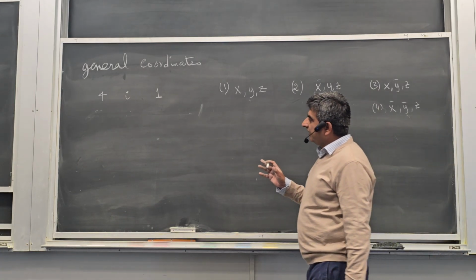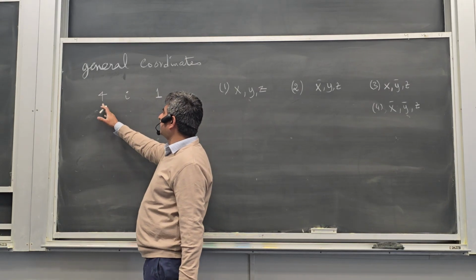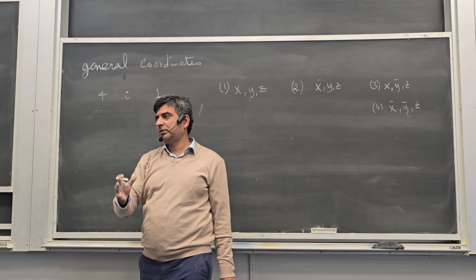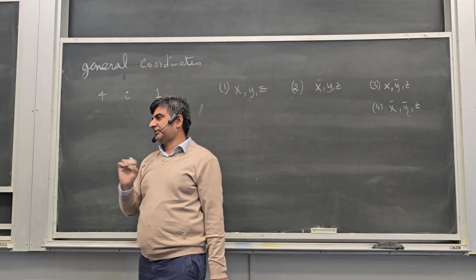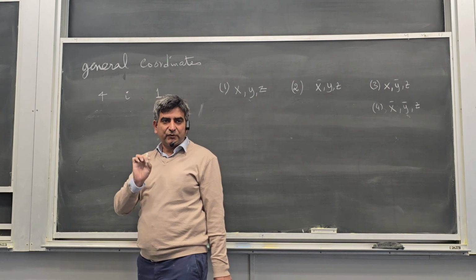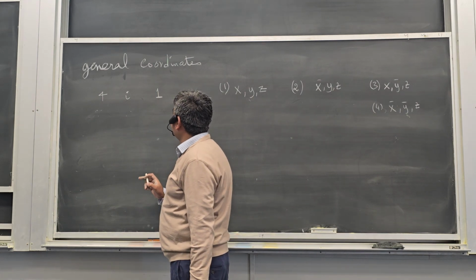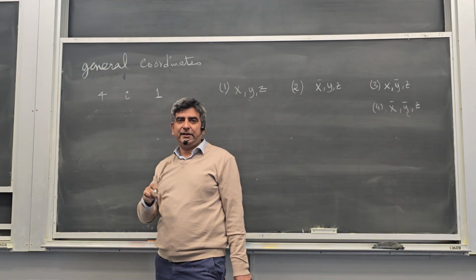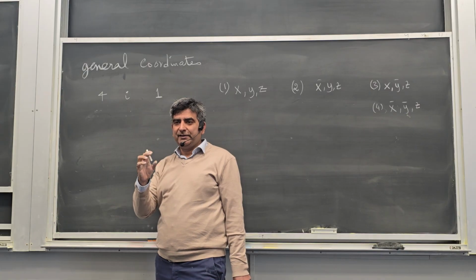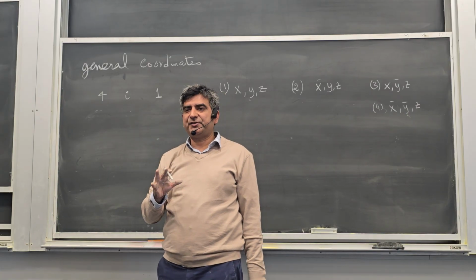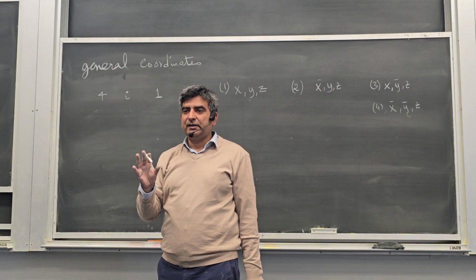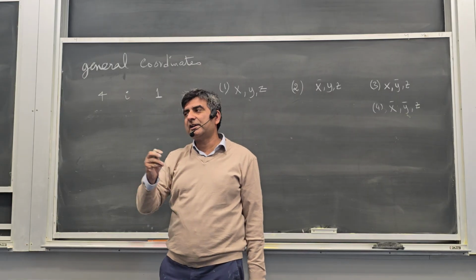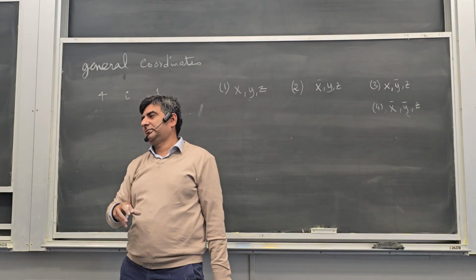So now I can tell what these symbols mean. 4 means that we have defined the general position x, y, z as having multiplicity 4. 4 locations must coexist, so the multiplicity is 4 for this general position. And the symmetry that exists at this particular point is 1. With these 4 points, no additional symmetry is needed. No additional symmetry element needs to be defined. Then just take those 4 points and put them here.